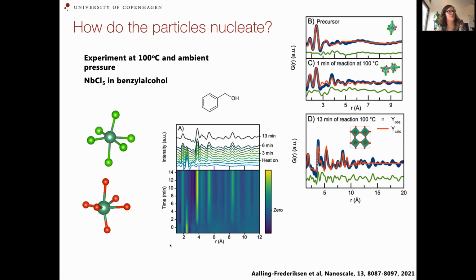Here we could model the first peak, this is our first PDF, the precursor. Then 1 minute into the reaction, we could see we had a peak forming here. That's a niobium-niobium distance. So that shows that we start having larger clusters formed. Later into the reaction, we can start modeling these with some larger clusters. What's important is that we found that the reaction mechanism happens where these corner-sharing octahedra find each other first, and then much later on we get edge-sharing octahedra that then continue to develop.